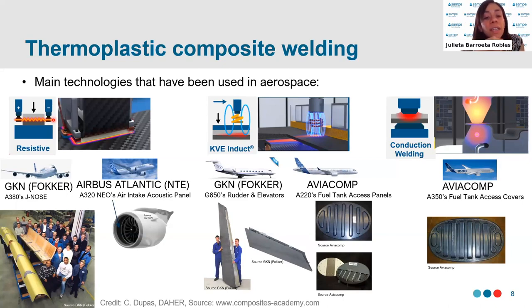The second technology is KVE induct. This technology was patented by KVE and follows the principle of induction welding, which involves passing an alternating current through a conductive coil, which is going to generate a magnetic field. Eddy currents are induced in the material, which are going to match the high frequency of this magnetic field, and then heat will be generated when energy is lost due to the resistance of the material. It is also possible to use susceptors or implants at the interface to concentrate the heat at this region. In the case of KVE Induct, there's a heat sink placed between the coil and the part in order to prevent overheating of the operative.